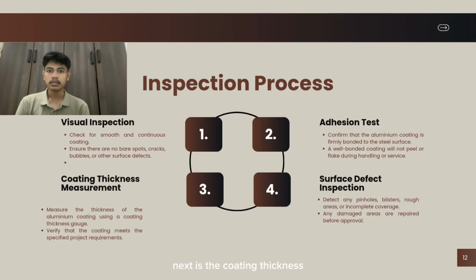Next is the coating thickness. The coating thickness is measured using a coating thickness gauge to ensure it meets its required standard. The coating must be thick enough to provide effective long-term corrosion protection. If any defects are found, the affected areas are repaired before the steel is approved for use. Only steel members that pass all inspection requirements are transported to the construction site.